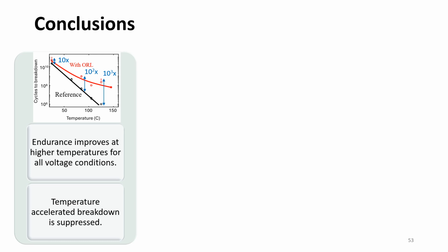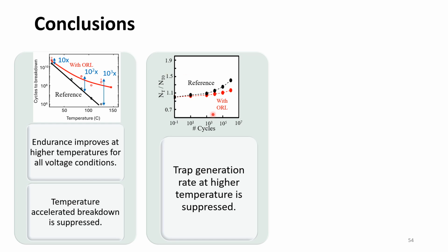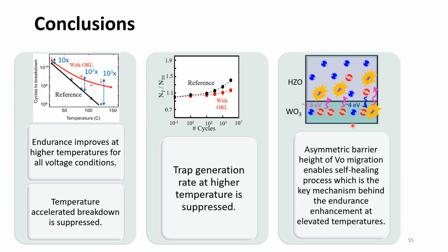So in conclusion, we can say that due to the presence of tungsten oxide layer in the ORL device, we are getting improved endurance up to 3 orders of magnitude at 125 degrees Celsius, and we are able to suppress the temperature accelerated breakdown in this device. This is happening because the trap generation rate at high temperature is getting suppressed in the ORL device, and this is possible due to the asymmetric barrier height for vacancy migration, which is actually enabling the self-healing process, which is the key mechanism behind the endurance enhancement at elevated temperatures.